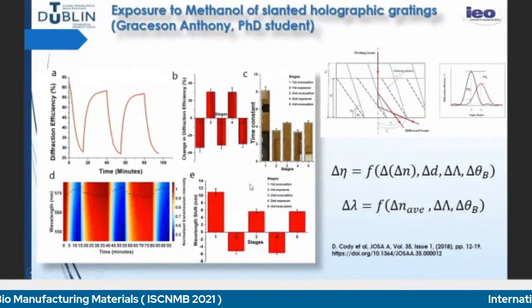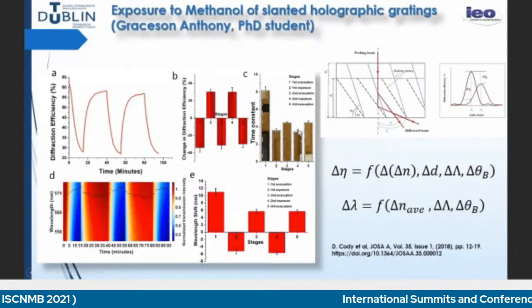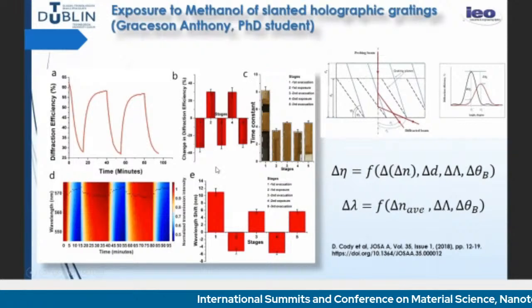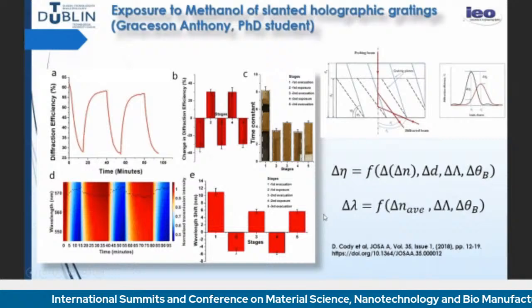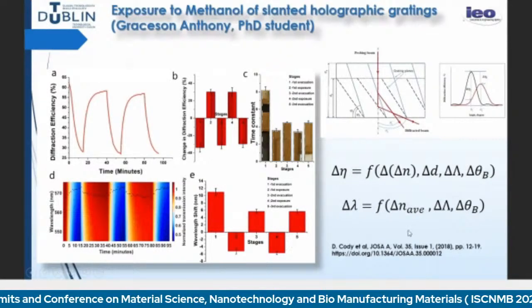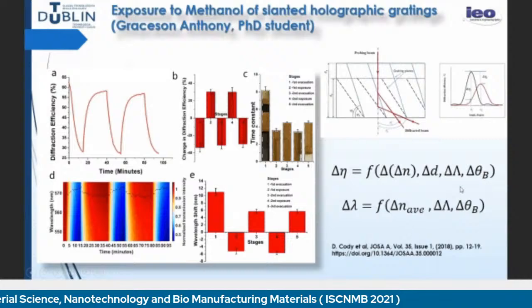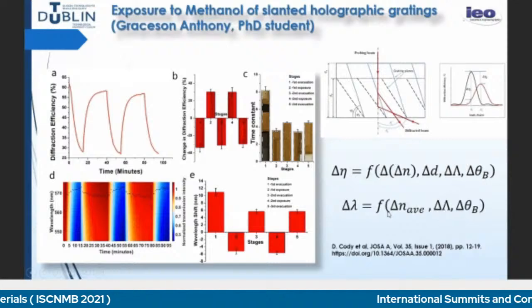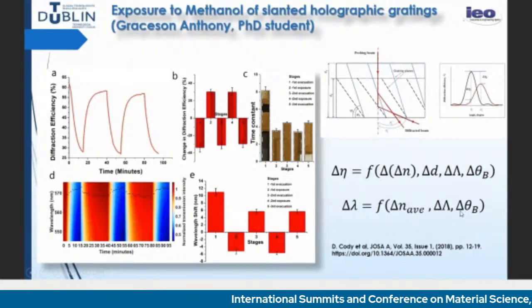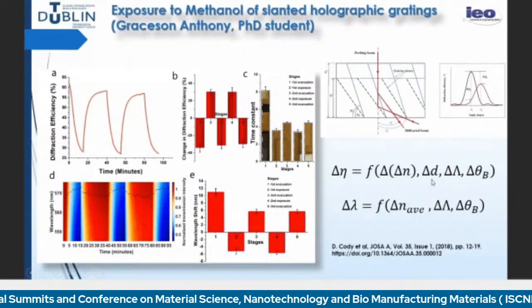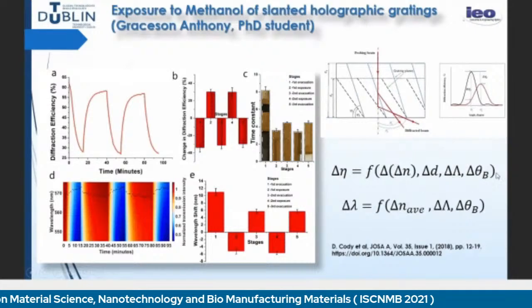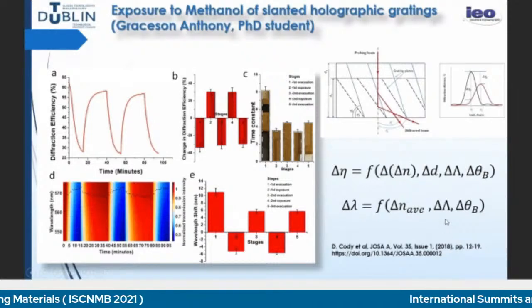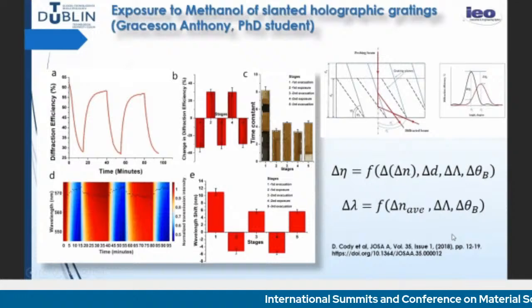This is a change in diffraction efficiency. The time constants are quite high at the moment, but he has used a relatively thick layer, which is 30 microns, and we can definitely go thinner. And this is the wavelength shift. So at the moment he is modeling: from the wavelength shift, we can determine the change in the average refractive index, the period and the Bragg angle. And from the diffraction efficiency, we can determine the change in the refractive index modulation and the thickness, which leads to change in the period and the Bragg angle, and thus extract separately the amount of change that happens in the material. But this is a work in progress at the moment.